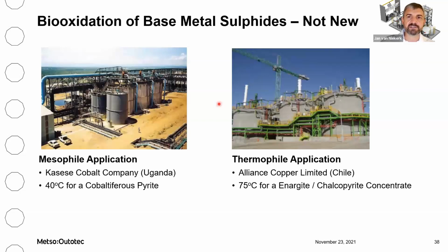Now, the bio-oxidation of base metal sulphides is certainly not a new technology or process. The first example of that on a commercial scale was the Kasese Cobalt Company in Uganda, which used it to treat a cobaltiferous pyrite concentrate. This plant operated for a number of years very successfully. And then Alliance Copper, the BHP Codelco joint venture, also demonstrated the use of thermophile bacteria for treating enargite chalcopyrite concentrate at 75 degrees C. This was done at the Chuquicamata mine in Chile. So it's certainly not new technology. It's, I think, relatively well proven in the industry, but just hasn't found wide application yet.